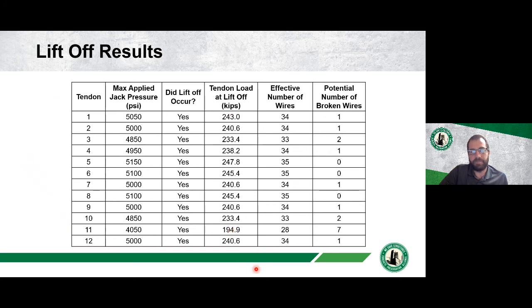And so based on some original drawings, we knew what the load of those cables should have been. And so we can effectively understand what the effective number of wires still is in that, if there's potentially broken wires. So the expected load of the cables was supposed to be around 245 kips. Each tendon should have had about 245 kips on it. And so if we saw loading less than that, then we knew we potentially lost a few wires, or there's some relaxation. You can see that tendon 11 only lifted off at 194. So potentially there's almost 7 wires broken. So the effective amount of wires in that cable is only 28. So we were able to go through and identify what the effective load is on each one of those, and how many effective wires there are.